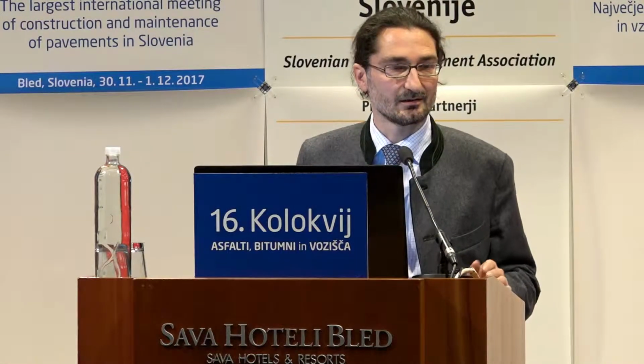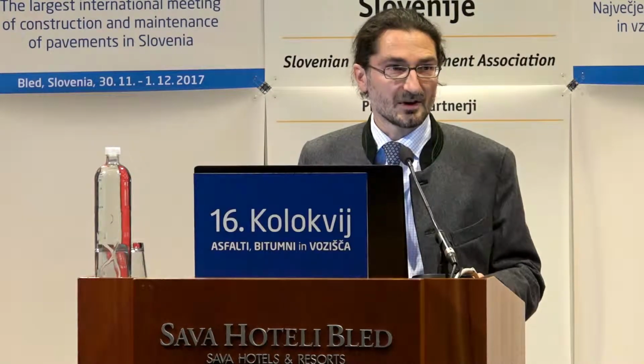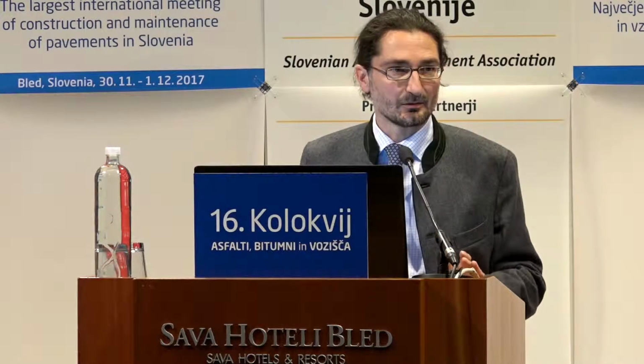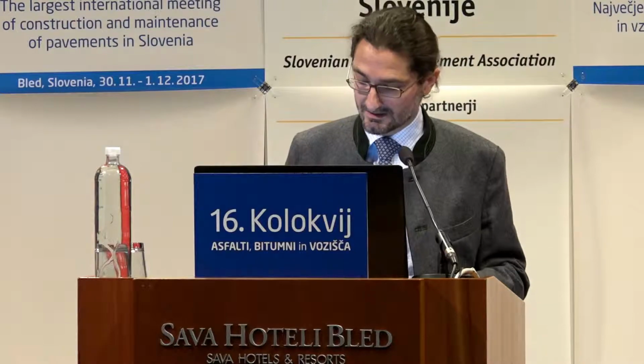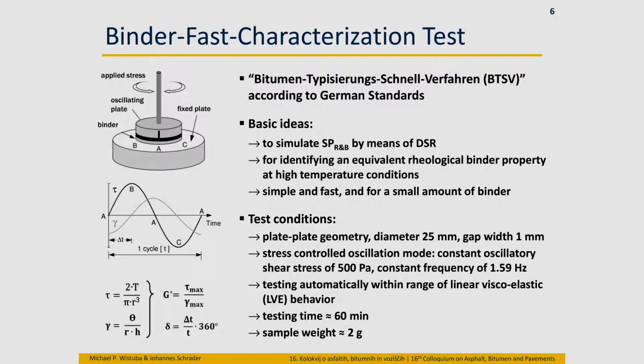Bitumen type characterization by softening point and needle penetration, as you can see here for typical German products, doesn't work very well. You can maybe differentiate very well with needle penetration, but just the non-modified binders. And as far as the softening point is concerned, there is a big scatter, and we are not able to precisely tell you the characteristics of asphalt materials with such modified binders. We have big problems. We will not be able to improve asphalt quality by not knowing the binder properties correctly. So there are two conclusions.